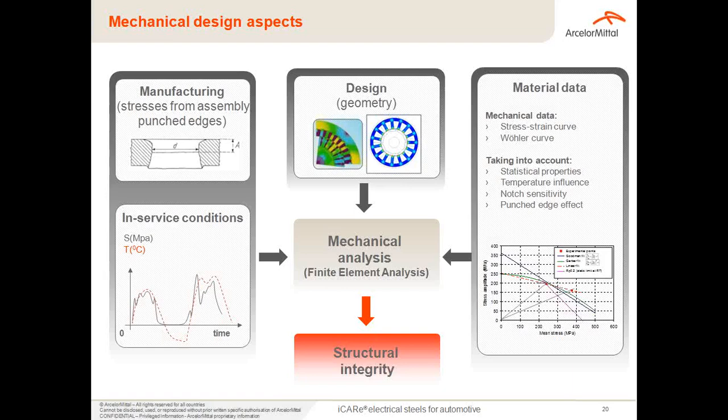So the point which is quite good to represent all this data is to work with the classical fatigue curves, and also to represent it on a diagram as we do here, where you have a representation of the static performance that says you need to be at the left-hand side of this pink graph in order to be in a safe exploitation area in order to stay below the yield strength limits, and those fitted fatigue limits that tell you you need to stay underneath this fatigue area. So in fact the total limitation of the exploitation of the material is a combination of the fatigue limit here at the left hand side of the graph and then the yield strength here.